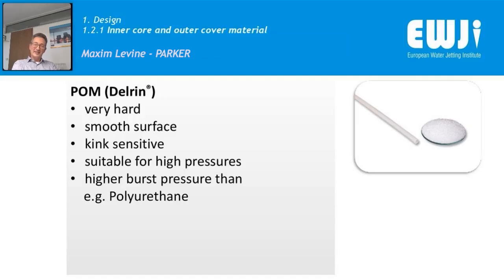This material is used in the high pressure hoses. Start with tube cleaning, 1,000 bar, 15,000 psi and above, and all the highest pressure hoses above, let's say 2,000 bar, 30,000 psi, are utilizing only polyoxymethylene. And the reason for that is that the mechanical properties of this material are so high that it is in fact the only alternative for this very high pressure.